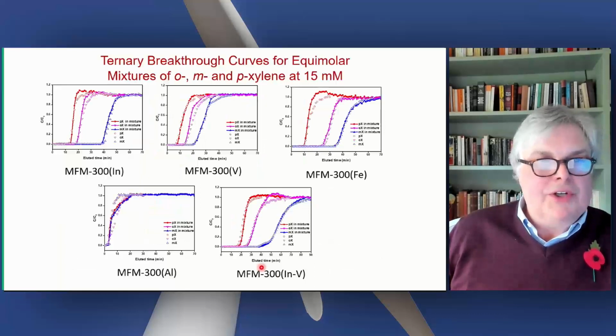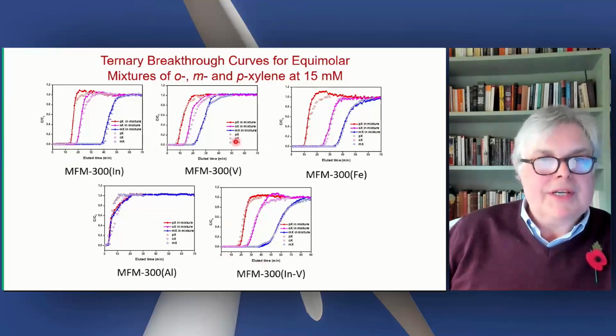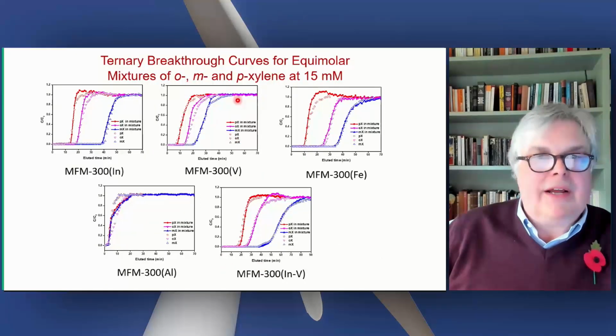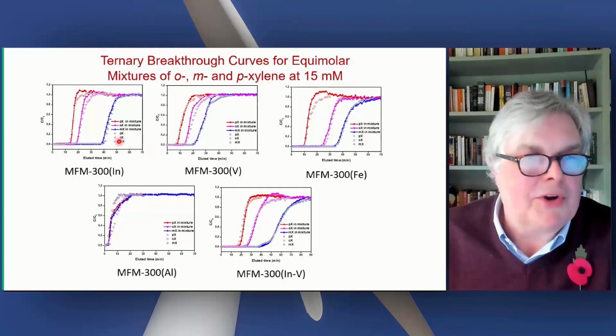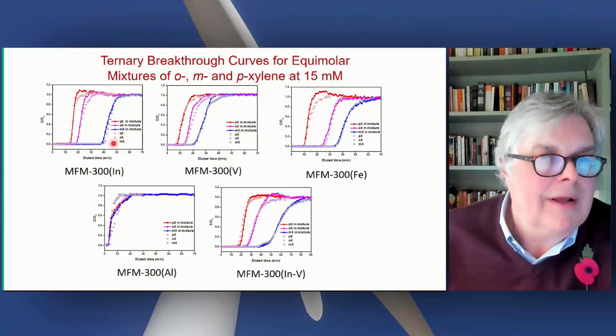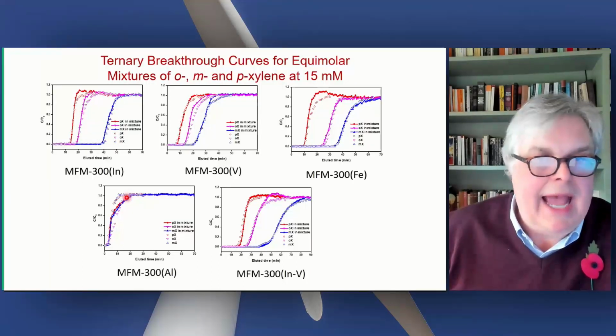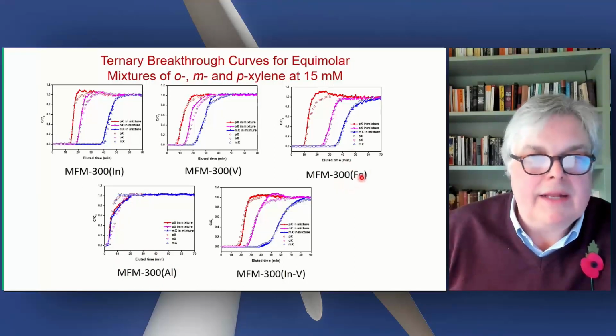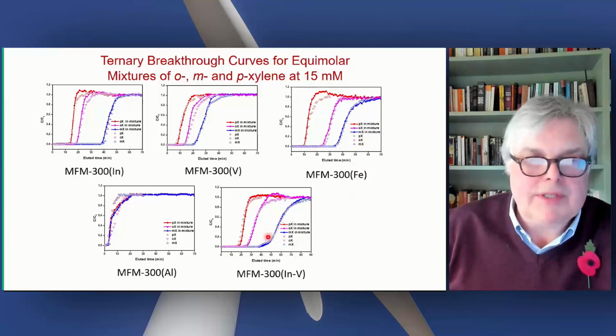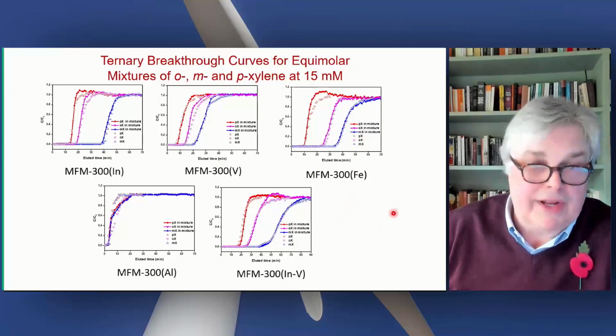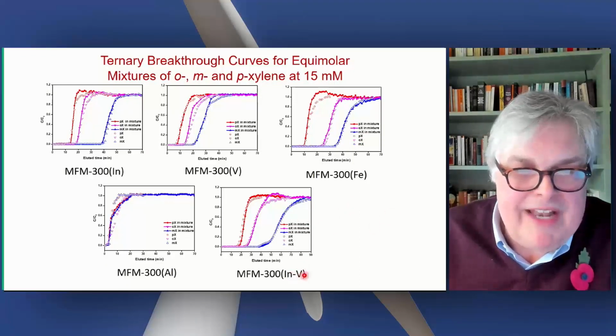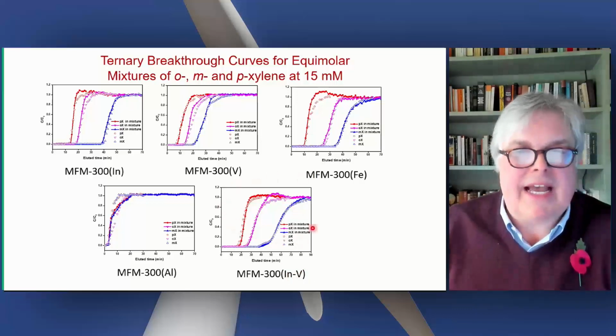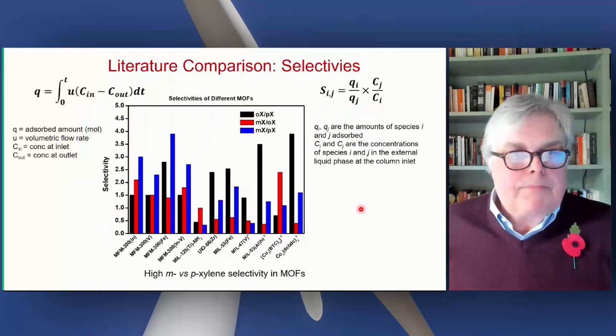And we can also do ternary breakthroughs with mixtures of ortho, meta and paraxylene, and also compare them with the pure components and make sure that it all is self-consistent. And again, you see the aluminium is really quite poor. The iron looks, at least under these conditions, to be one of the better ones, together with the vanadium system. Oh, sorry, this is the mixed indium vanadium system. So you can see that that is actually the best one.